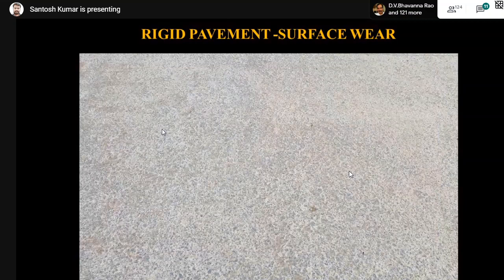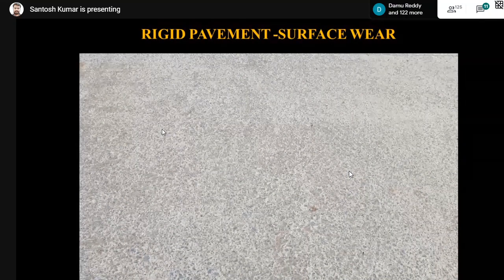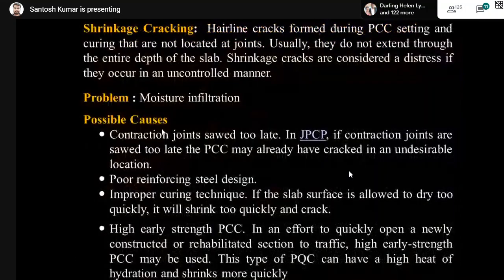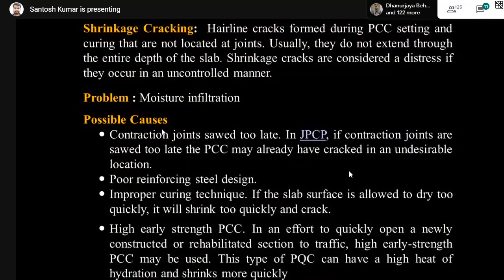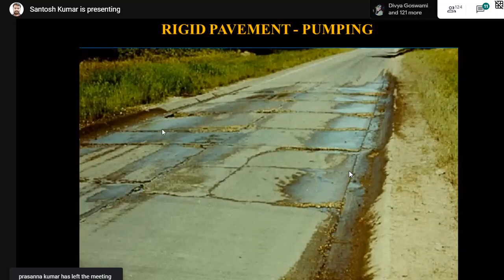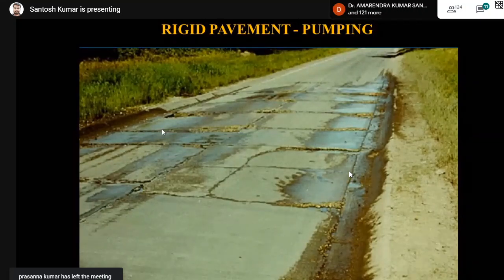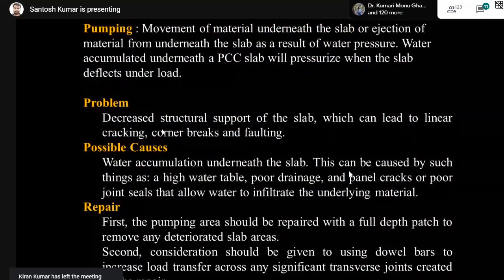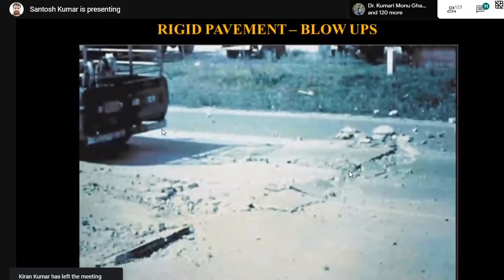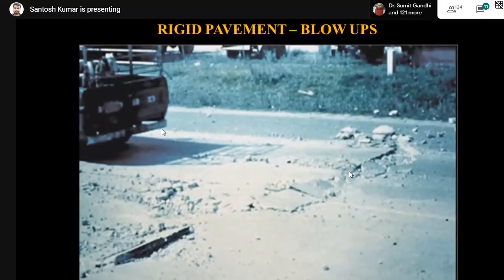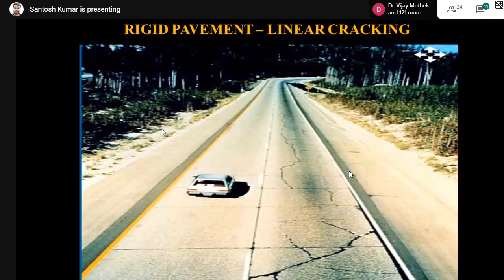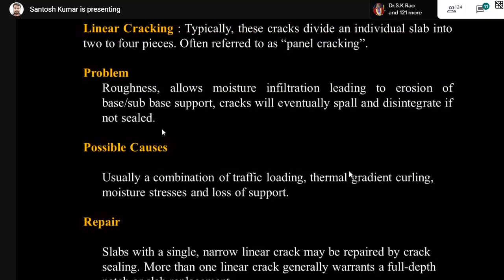And some problems related to rigid pavements are also the surface wear. Freshly laid concrete, there is a surface wear because of lack of strength of concrete. You can see the shrinkage cracks in concrete. And there are a lot of problems related to shrinkage cracks, as already discussed. If the contraction joints are lately sawn, there may be chances of shrinkage cracks, and they have to be addressed in a proper manner. This is also one of the distresses, I can say, mud pumping or pumping of water underneath the pavement. It breaks the concrete slab, and there are corner breaks and linear cracks observed. And there are some blow-ups due to the temperature variations inside the concrete, and they can also be rectified by removing and replacing the entire panel, and some linear cracking also is seen, and there are some problems related to that also.